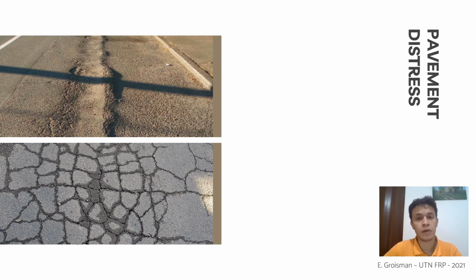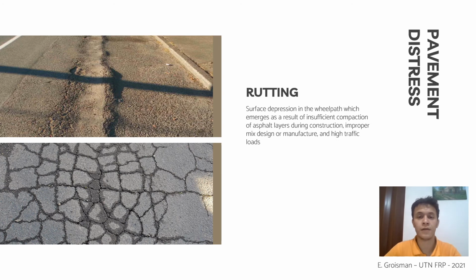Where using crumb rubber improves the resistance to this kind of pavement distress. So let's begin by talking about rutting, which is a surface depression in the wheel path, which emerges as a result of insufficient compaction of asphalt layers during construction, improper mix design or manufacture, which is what we are studying here, the mix design of the crumb rubber modified asphalt, and high traffic loads.